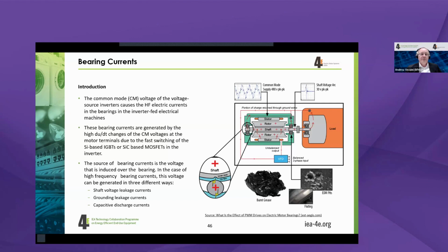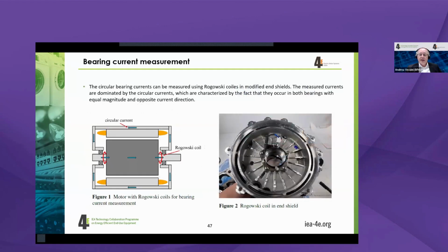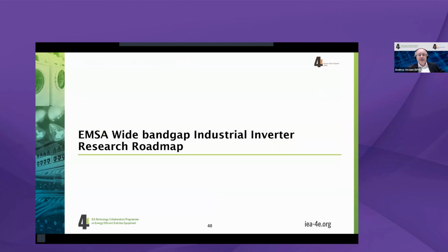Another ongoing test is the impact of the high switching speed of the common mode voltage, which will have an impact on the bearing currents, and the bearing currents then create basically grooves inside the bearings, and the impact can be seen there. We are measuring these by adding some Rogowski coils inside the end shield of the motor to detect how much impact we have from this.